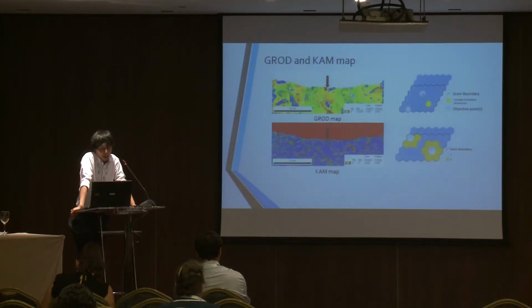Next, GROD and KAM maps are shown. The GROD map represents the orientation difference from a certain reference point within one crystal grain. As a result, the amount of local plastic strain can be measured. In the vicinity of the trigger MA, there are places where the value of GROD is very high, shown in red.